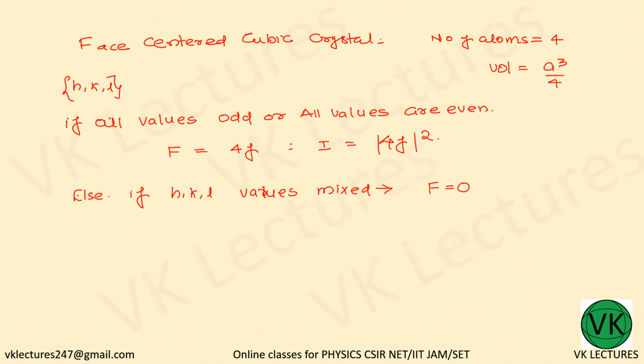Okay, so which implies that for the face-centered cubic crystal, if the values are all odd or all even, then we have a Bragg reflected plane.